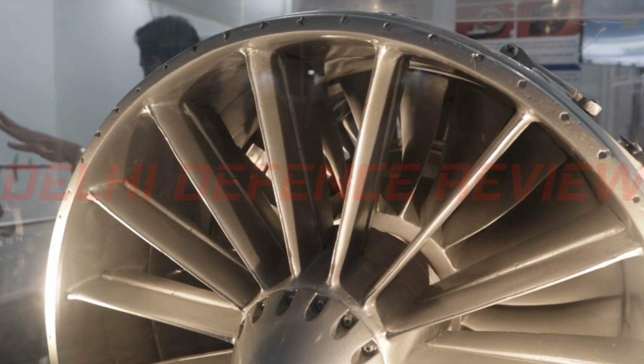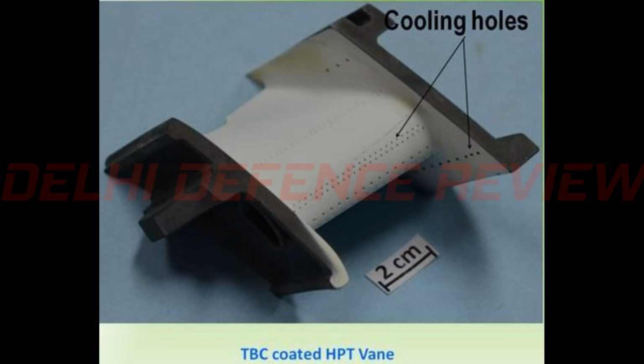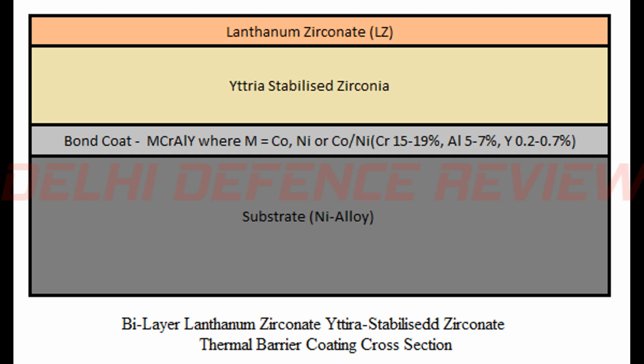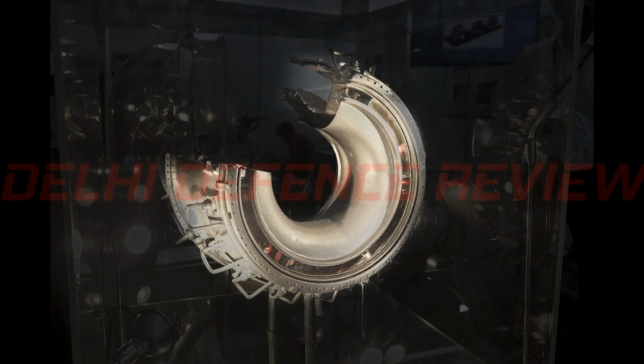The Defense Metallurgical Research Laboratory (DMRL) has developed single crystal turbine blades coated with a thermal barrier coating of yttria stabilized zirconia. The coating was applied via a process called electron beam physical vapor deposition by ARCI Hyderabad. Also, another thermal barrier coating which features a layer of lanthanum zirconate over and above the yttria stabilized zirconia has also been developed by DMRL. So far it has been proven on static portions of the engine and might see application in the combustor and nozzle flaps.